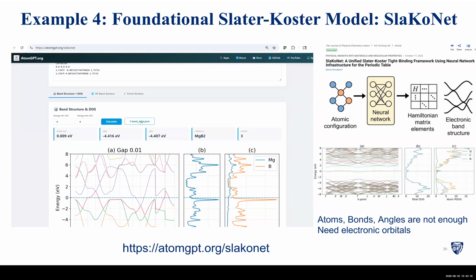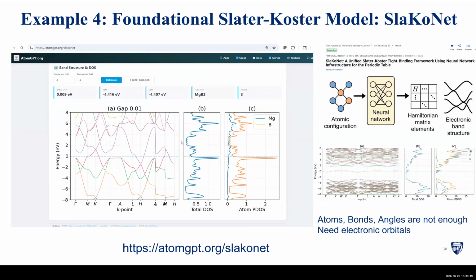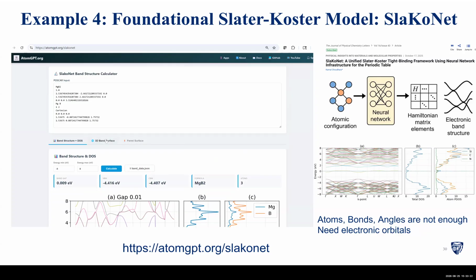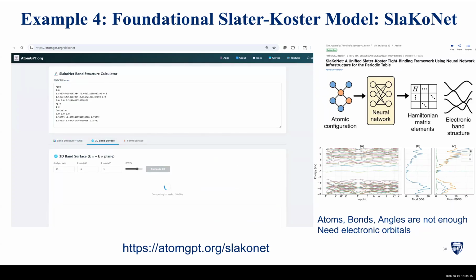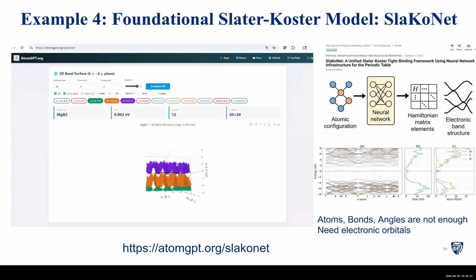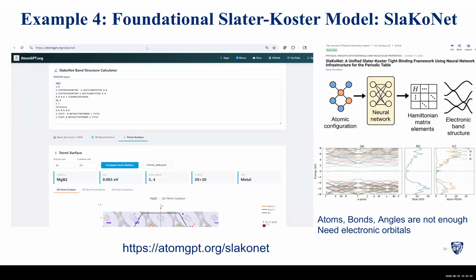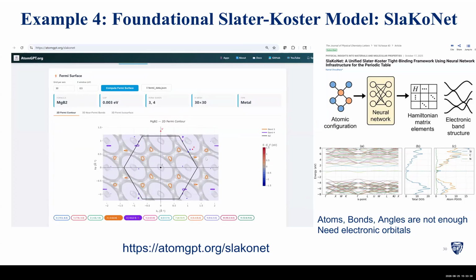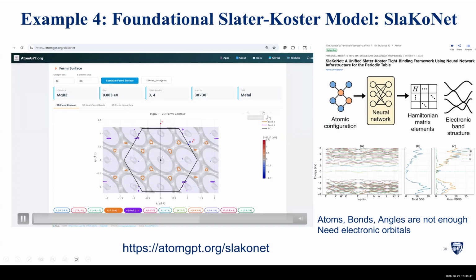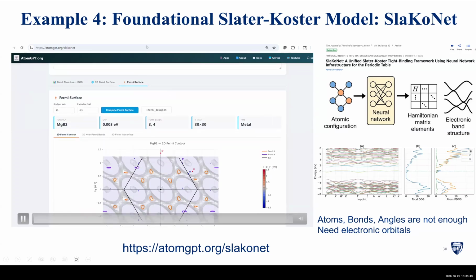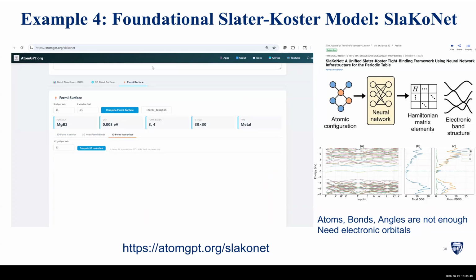So you can get the band structure, atom-projected density of states, orbital-projected density of states. You can get a fancy 3D visualization of your band structure if you like, which is important for something like ARPES data. You can get Fermi surfaces, which are important for metals, and so on. All from a click. You don't have to know any coding. You don't have to know VASP, Quantum ESPRESSO, and so on. It's only limited in that it cannot do lanthanides and actinides right now, which we are working on. But any other combination of periodic table elements you can simulate with this.